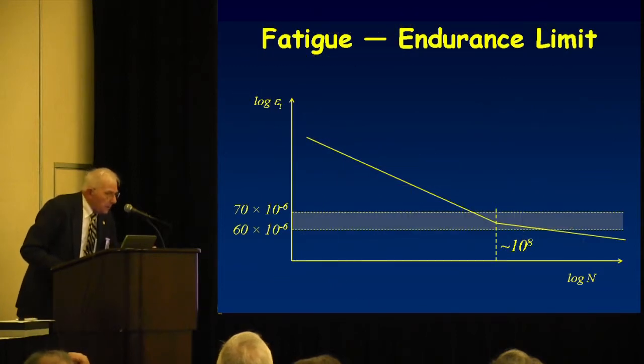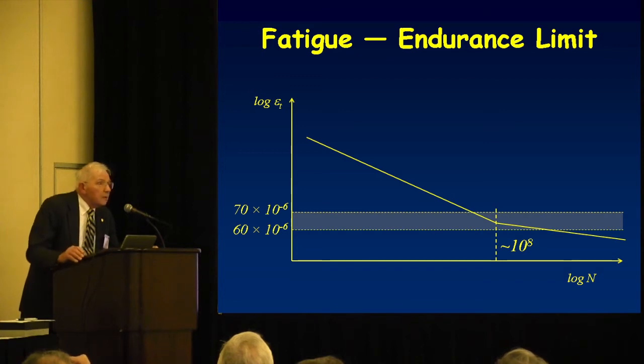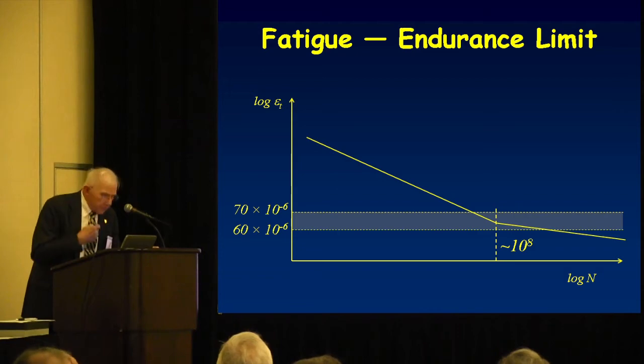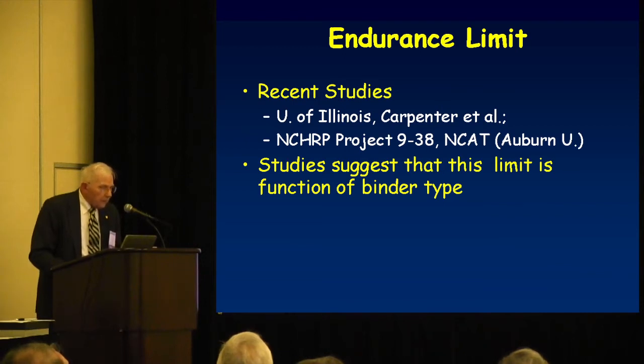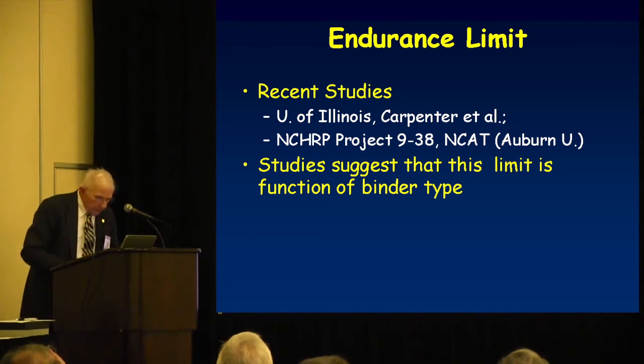Now, the problem is, in the case of fatigue, it turns out that once you get to very low strains, there seems to be a change in the slope of the line. So some people have called this an endurance limit. And so at least for conventional asphalts, it looked like it was in about the range of 70 to 60, 10 to the minus 6 strain, and around 100 million repetitions. And so people have been looking at that more recently, and very nice work has been done at Illinois by Carpenter and the NCHRP projects. And these studies have indicated that maybe, depending on the type of binder in the mix, there may be different strain levels where this might happen.